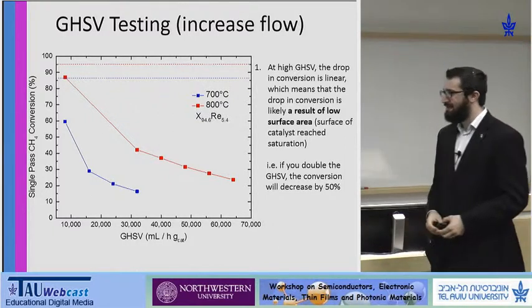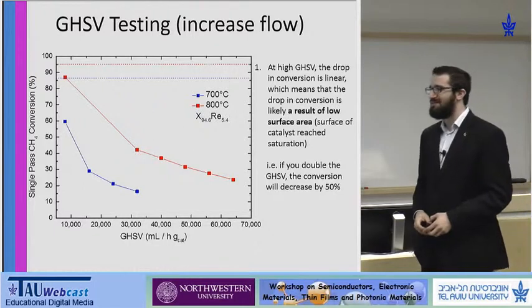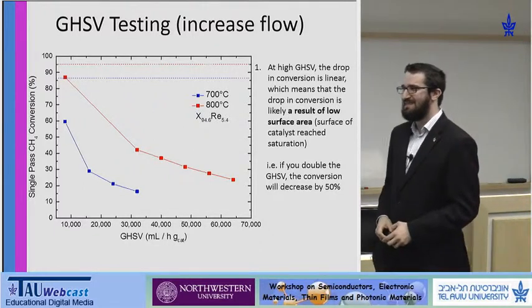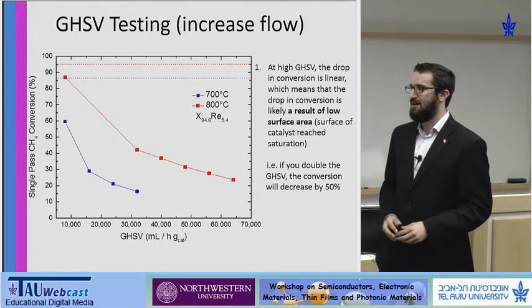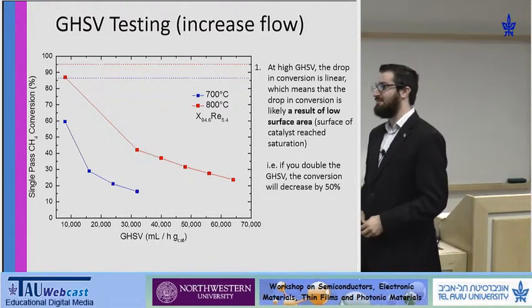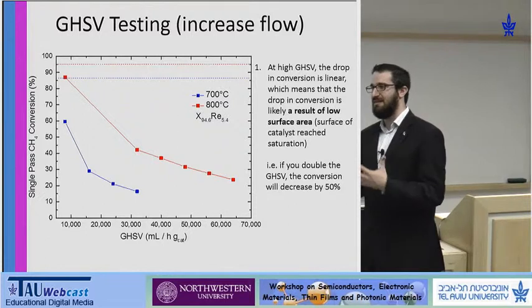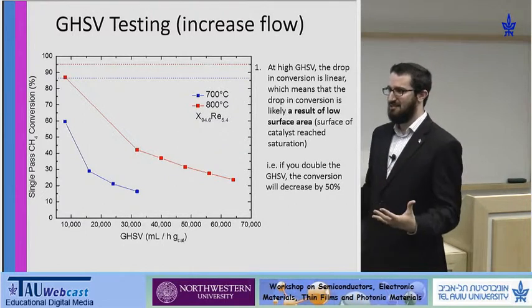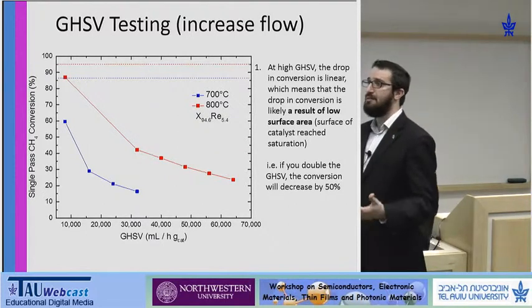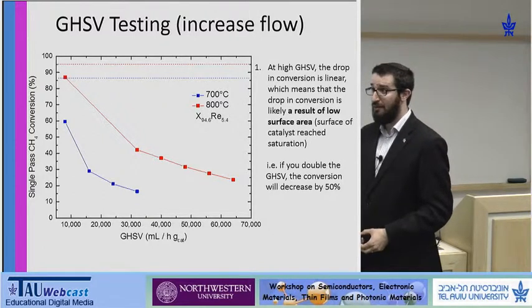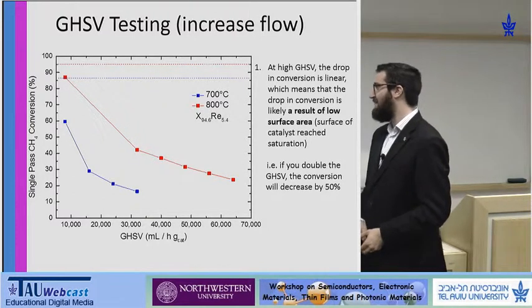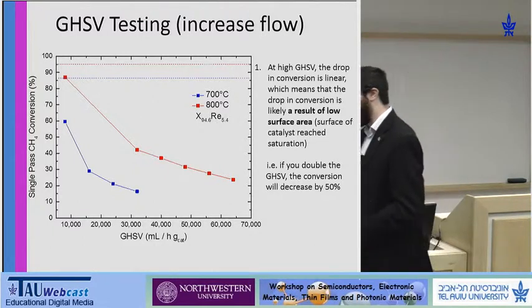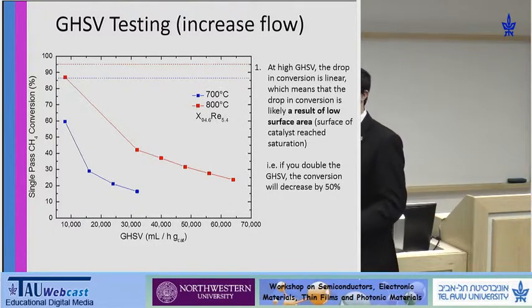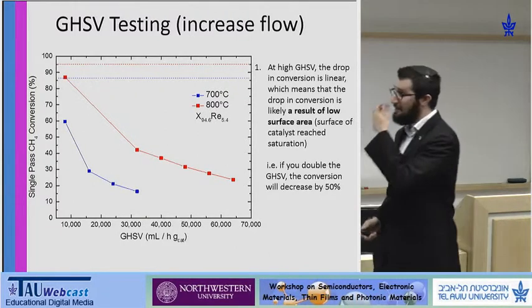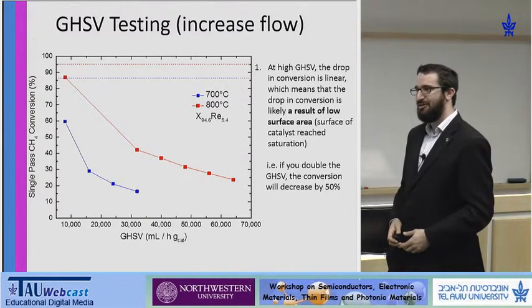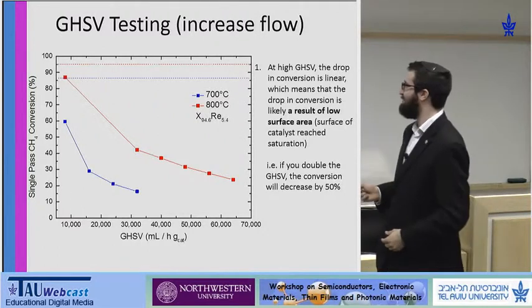I should mention that this is significant because nowadays people don't talk about using metal meshes and fibers and cloths as catalysts, not nearly as much as they talk about using powders. This is a consideration of surface area. So the fact that we've developed a metal structure that's highly conductive, that has a surface area likely one or two orders of magnitude lower than a powder, yet can perform at about half the performance, so less than an order of magnitude difference, this is significant in the field of catalysis. And we're going to be doing BET measurements in the near future so that I can quantify that last remark.